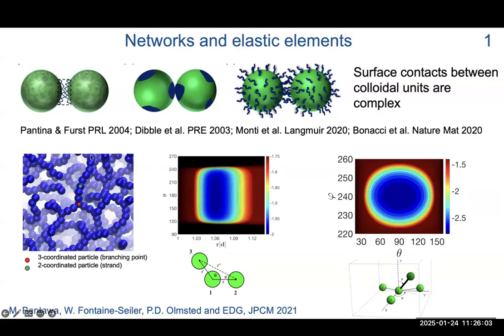So I have gel branches that I can easily identify because they are made by basically chains of these particles, and they can branch, as you can see here, and the branching points are easy to identify because they are just particles with coordination number 3. So this is a model gel structure that we have used to study the disorder that can emerge in the formation of this structure, which is always a very interesting type of correlated disorder, which can then lead to some effective organization and functionality of these materials.